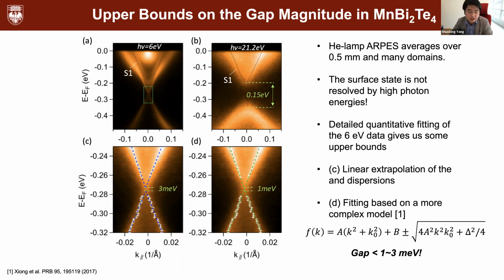And I would say the most likely scenario, in my opinion, is that the spin configuration on the surface is different from the bulk. We resolved these quasi 2D bands, but in our model they are surface related, though not only on the very top surface. In our picture, this is actually a quantum well. In a quantum well, your states are quantized, so depending on the levels, you have different spreads of wave functions. So in our language, these quantum well states are different from the surface state. But what exactly happens on the surface that kills this substantial broken symmetry, that's the part I could not answer. The best I could answer is that it's probably not as strong as what the theory suggests. Yeah. Thank you.